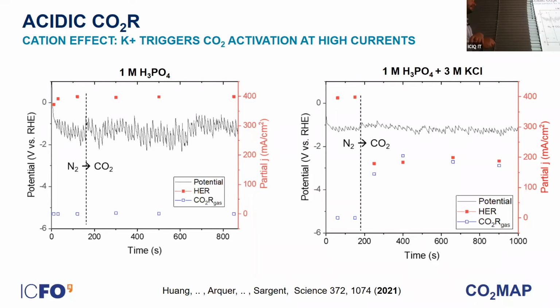We mostly have hydrogen. I'm afraid you cannot see the right axis here, but the point of this plot is that when we add some potassium cations into the system, something very funny happens. The partial current density for hydrogen, the square red points, decreases, and conversely, the partial current density for CO2 reduction increases by the same amount, interestingly, without changing the overall potential. So that means that when you have cations in the system and you have CO2, CO2 is getting reduced.